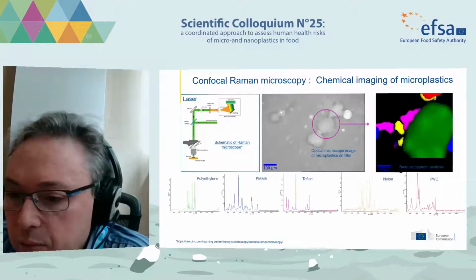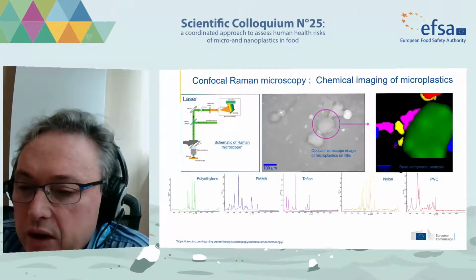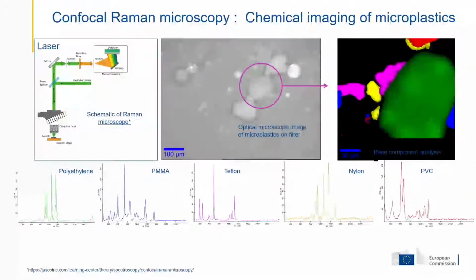When this particular type of equipment is integrated together with an optical microscope, which allows very fine focusing of the laser, it becomes possible to acquire Raman spectra from very small regions of the samples. By scanning and mapping, it becomes possible to produce chemical maps of particulates and materials over areas of microns, hundreds of microns, or larger.